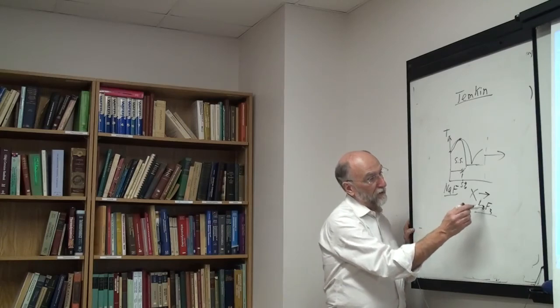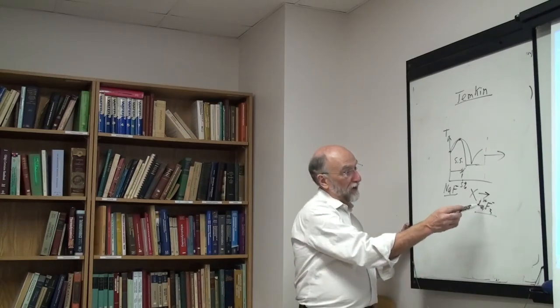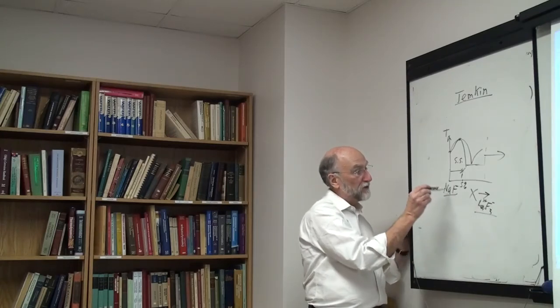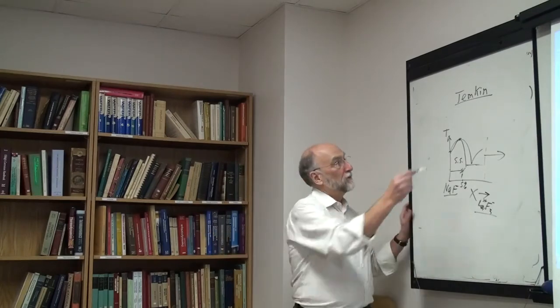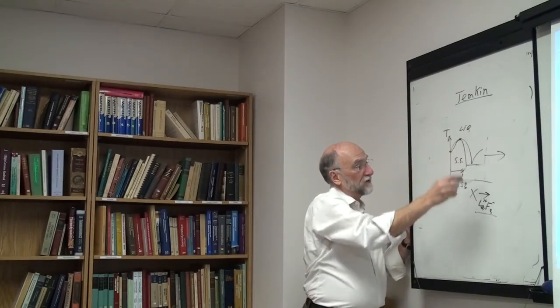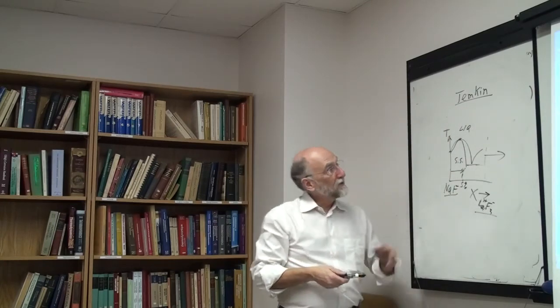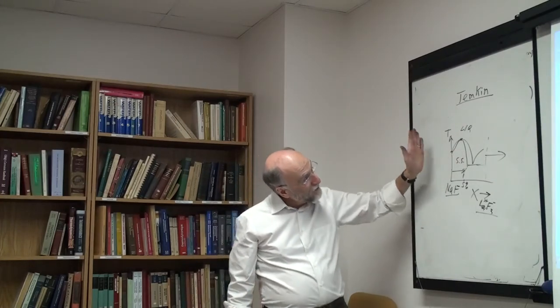So remember, lanthanum fluoride is the same thing. This is lanthanum 3+, fluorine-. So if in the solid solution you add lanthanum to sodium fluoride, you're putting in lanthanum and you're forming two cation vacancies. If you put lanthanum into the liquid phase, however, the Temkin model applies and you're only forming the lanthanum. So what's happening is the solid solution is entropically stabilized, at least for a small region.